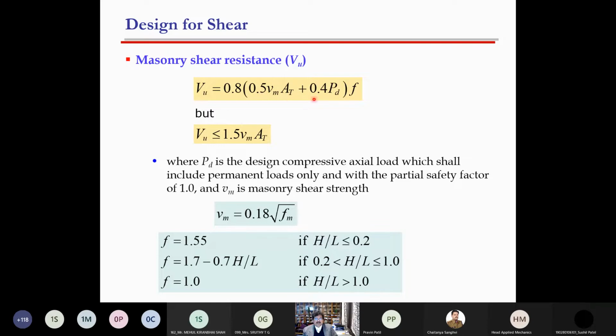So this is that, and then this is the friction factor times axial load. And then there is a reduction factor 0.8. And this F is the aspect ratio. Okay, so if it is very slender, H over L, then F is 1, but if it is square, then it is 1.55. These numbers come from experimental curve fitting to the data that we had. And the VM is masonry shear strength, which is related to the compressive strength of brick prism. So you take 5 bricks stacked with the mortar and test under compressive load. So that gives you fm, and this is 0.18 root fm, very similar to what we do in case of concrete. All the shear properties, etc., have square root terms of your compressive strength.